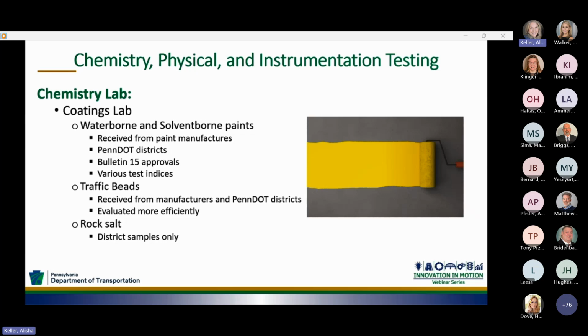All the material received must be Bulletin 15 approved. The lab conducts various tests on each product, and each product has a lot number assigned from the manufacturer. We compare the results we obtain from the manufacturer's sample with the results obtained from the product received from the district just to make sure that the sample not only meets specification, but that the product is a representative sample.